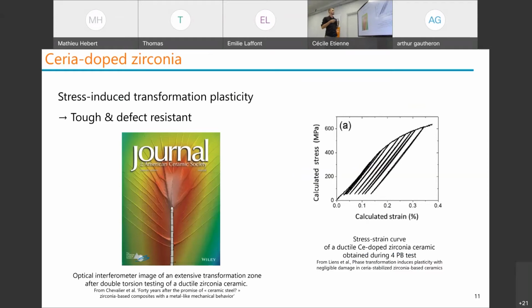And you see the term plasticity that might make you scream if you're a ceramist. But in fact, we can have a good toughness even if it's a ceramic and avoid brittle fracture, as you can see on the strain-stress curve, because the crystallographic structure changes when you apply too much stress, and you can see it here on the left.